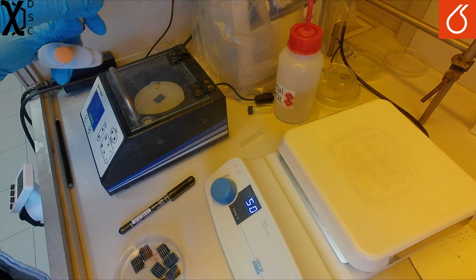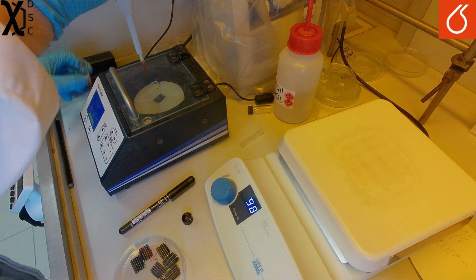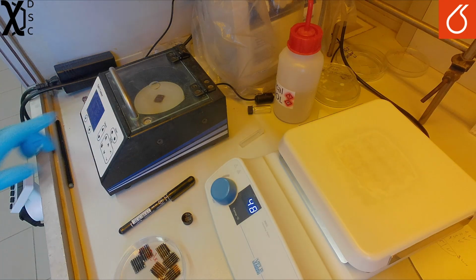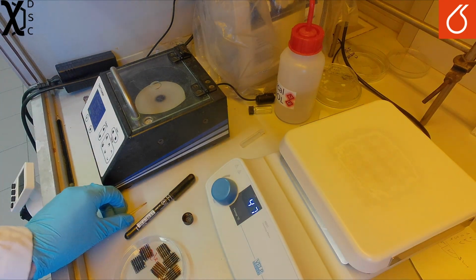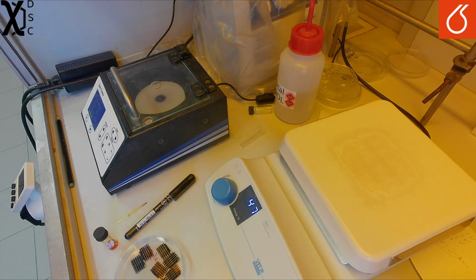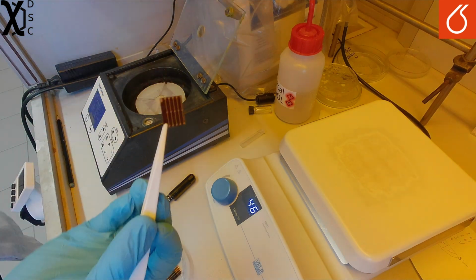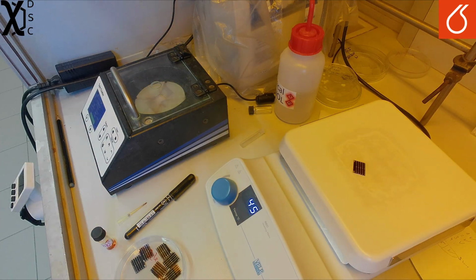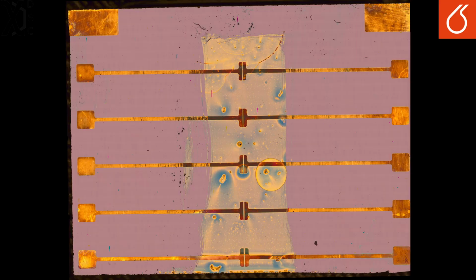In order to do this, commonly a quantity of solution is deposited onto a substrate and then it is spun at a prescribed speed. Here I am using 100 microliters of 5 mg per ml P3HT in a 1:4 mix of chloroform and orthodichlorobenzene. It is also possible to deposit the compound while the substrate is spinning. However, how well this method works will depend on the substrate.